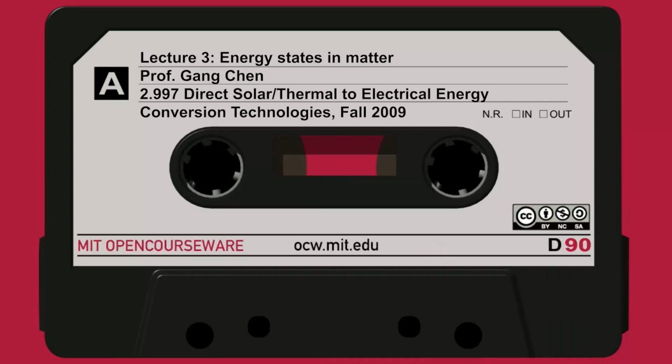Okay, so you're asking what are the wave vector numbers? This is where, the number of waves when I go from here to here. This is called from minus pi over a to plus pi over a. That's called the first Brillouin zone. And the number of wave vectors k equals the number of atoms you have. So from here to here, the number is n.